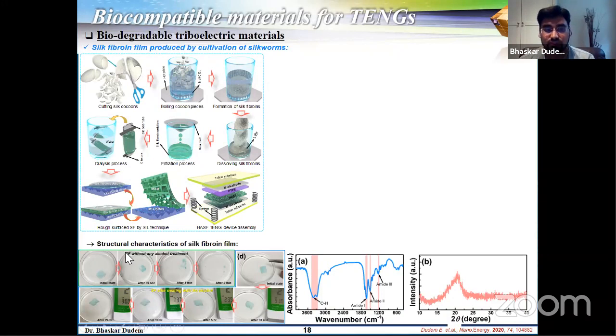For example, if we see the first four images here, we did not perform any alcohol treatment on the silk. It degraded within 3 minutes. When we treated it with alcohol, it sustained more than 24 hours. It even sustained for several days. So in a humid environment, it can be sustained very easily, and it can continuously convert mechanical energy into electricity. The most important feature of triboelectric nanogenerators is to be sustained in a humid environment, because humidity can highly influence the performance of triboelectric nanogenerators. So we have to make the material withstand humidity.